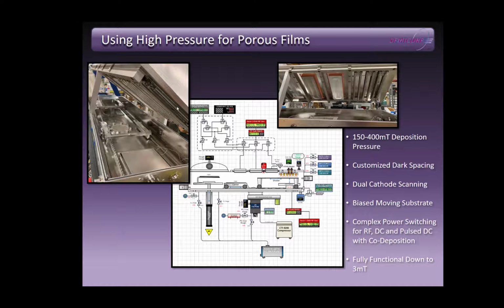This scale-up would require very high pressures during sputter deposition to achieve the porosity desired, in some cases as high as 400 millitorr. The high pressures created dark space issues for the cathode as well as other areas of the process. We utilized some gas distribution techniques as well as unique dark spacing that would also allow for normal deposition pressures down to 3 millitorr.